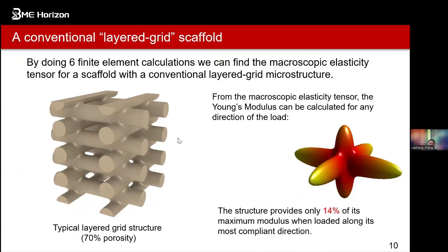We can produce the structure. That's, for example, the traditional layer grid scaffold. We can put it layer by layer, and of course we control it. But actually, this is a big issue because these kinds of structures produce a lot of inhomogeneous elastic Young's modulus. You will see the Young's modulus in the least stiff direction has only about 14% of the stiffness of the most stiff. So this is typically